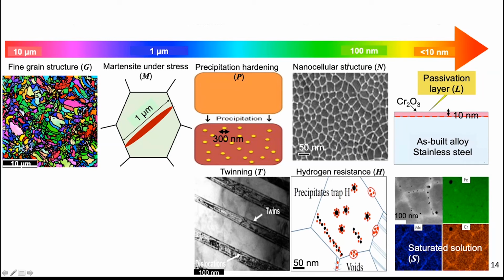And I'll start with the grain structure, which is what I said that metallurgists usually play with. The grains are responsible, in the case of additive manufacturing, for texture. Texture means that you can orient them in certain directions. And with texture, you can control the strength, but also the stiffness. Stiffness is really important because a material that is very stiff will not deform. And if it's not rigid, then it will be elastic. This is important, for instance, if I want to 3D print bone replacements, which is an emerging technology.